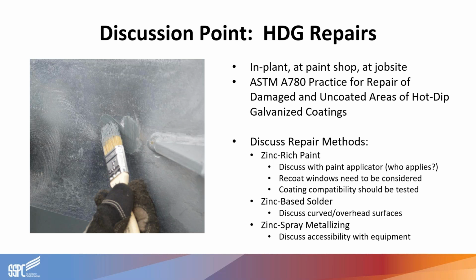There are 3 methods that are allowed for the repair of all hot dip galvanized coatings, according to the specification ASTM A780. Those 3 methods are zinc metallizing, zinc solder, and the use of a zinc-rich paint. Unless explicitly specified or agreed to, the galvanizer may select any repair material from this list. Regarding painting or powder coating afterwards, if you're utilizing zinc spray metallizing or zinc solder for the repair of hot dip galvanized coatings, there's not going to be any additional clarification required.